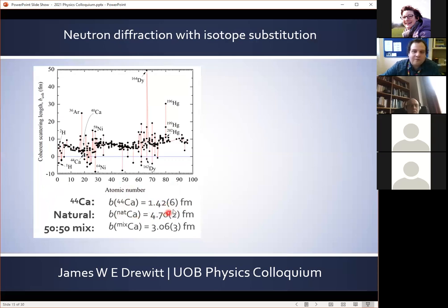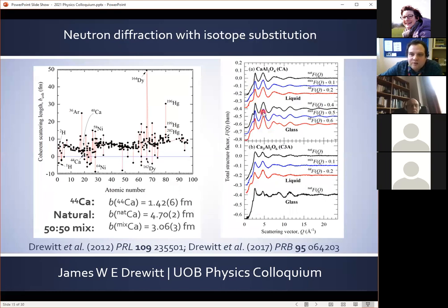And so if we can synthesize three samples that are identical in every respect, except that they contain either calcium-44, calcium in its natural isotopic abundance, or a 50-50 mixture of the two, then the correlations involving calcium will have different weighting factors. And so this leads to observably different structure factors.